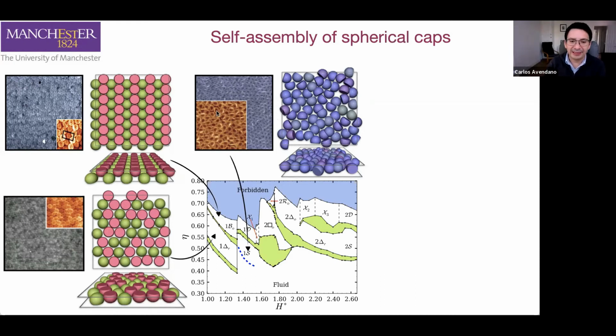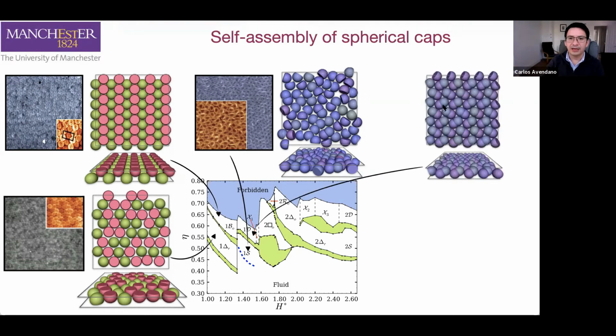And if we keep increasing the density of this system, so we move from that point to this density over here, what will happen is that the two particles in this side phase will come together, the two flat facets will align to each other, and they will form this kind of dimers that eventually they can also form a more ordered structure. In this case, they form this Herringbone structure.